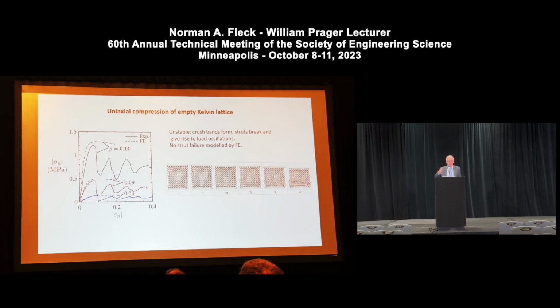One can vary the relative density, the T over L value of the aspect of the lattice. So here's the lattice. You can vary the thickness of the struts to the length, thereby varying the relative density from 4% up to 14%, and measure for the open cell empty Kelvin lattice the response. And what you see is oscillations in the load curve due to the formation of successive crush bands. We performed finite element simulations of this behavior, but did not put in fracture, and so we did not capture these crush bands that formed due to fracture of struts. But otherwise, the finite element simulations were able to capture reasonably well the modulus and the yield strength.